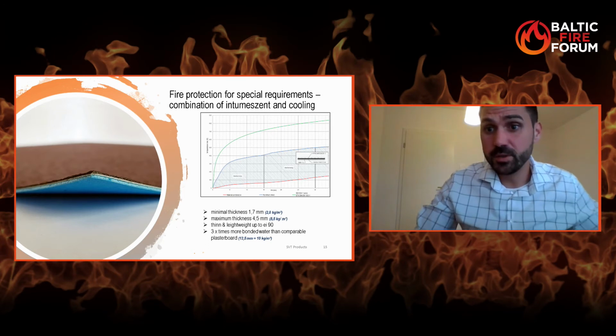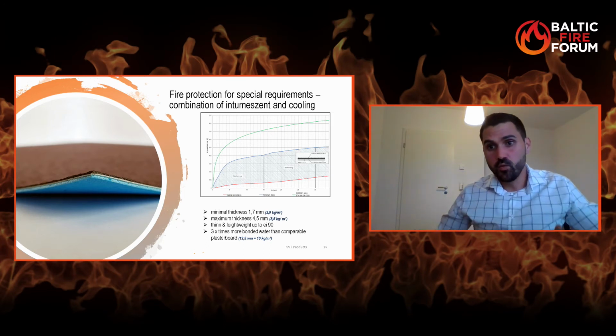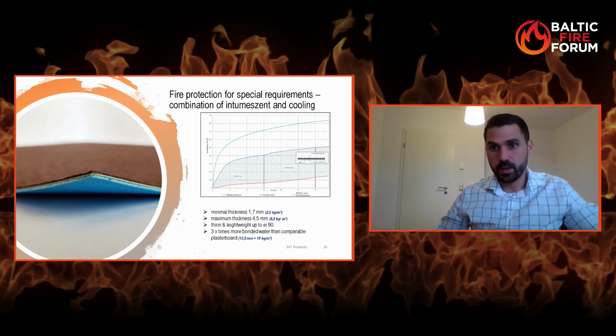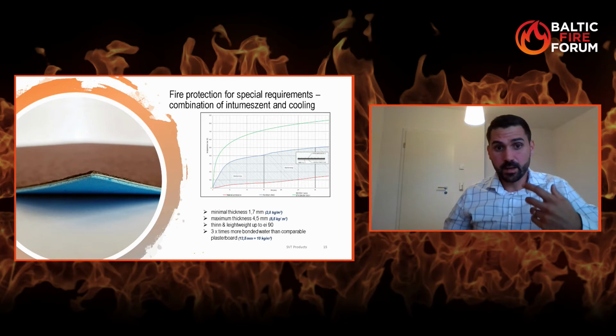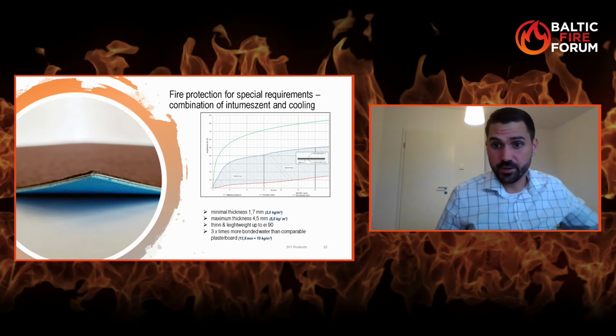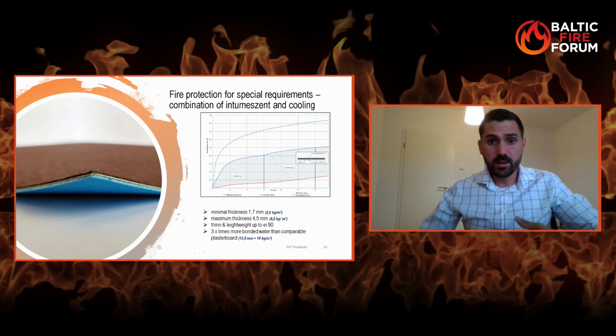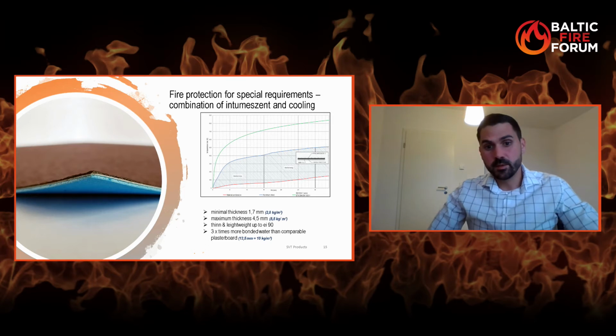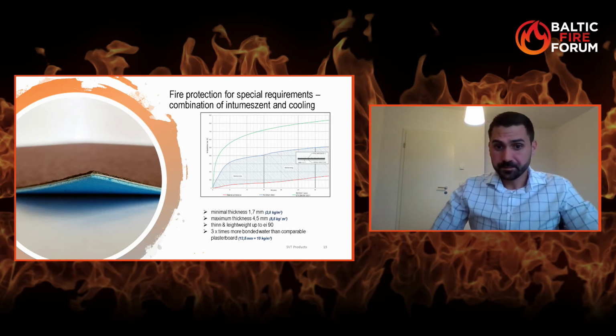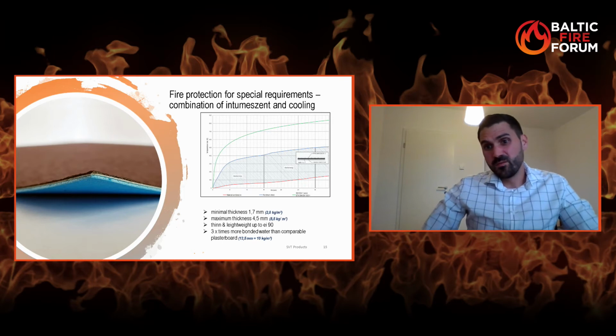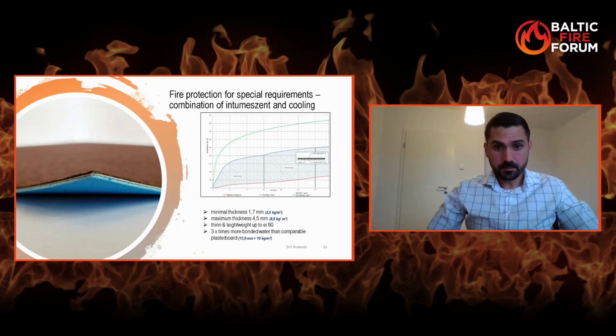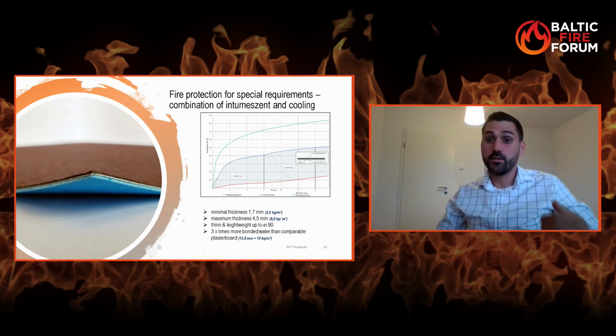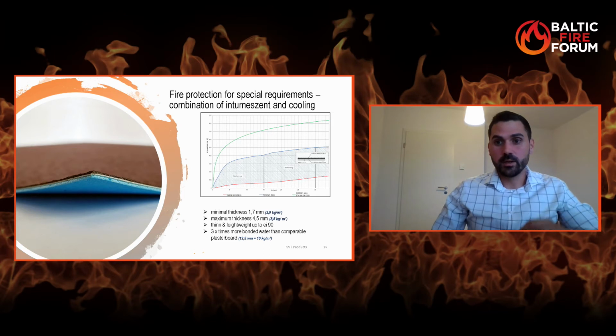Also, you can combine these two materials. As you can see here in the picture, you have the blue one, that's the cooling material, and the red one is the intumescent material. If you combine these two together, as you can see in the table, you can absorb so much energy from the fire and cool down the whole structure. You have a minimal thickness of 1.7 millimeters and a maximum thickness of 4.5 millimeters. You can achieve up to EI90 in a construction, but you don't really need 90 minutes in the case of a battery fire. And you have 3 times more bonded water than a comparable plasterboard. So you're thinner and lighter, and lightweight construction is our main focus.